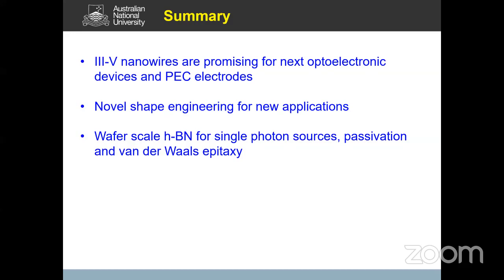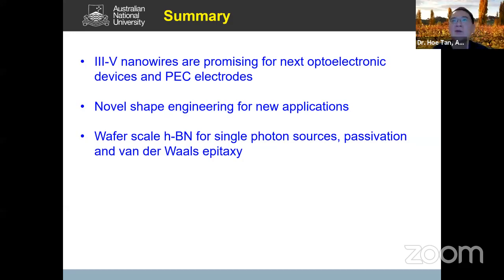they are asking how we can differentiate nanowire solar cells from nanorod solar cells. Nanowire and nanorods, okay. So these terminologies are interchangeable. Usually for nanowires, like gallium arsenide and indium phosphide, we can grow longer, so people normally call that nanowire. But for gallium nitride, people cannot grow that long. Typically they're limited to just 1 or 2 microns, so they call it nanorods. I suppose to some extent, it depends on the aspect ratio.